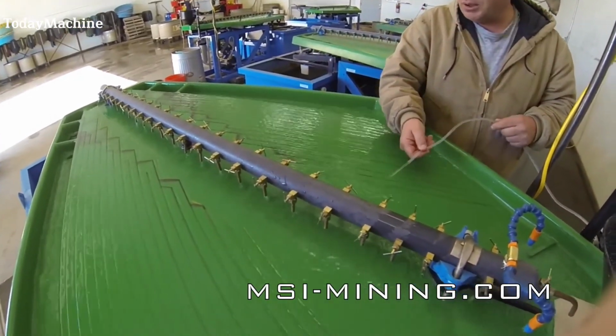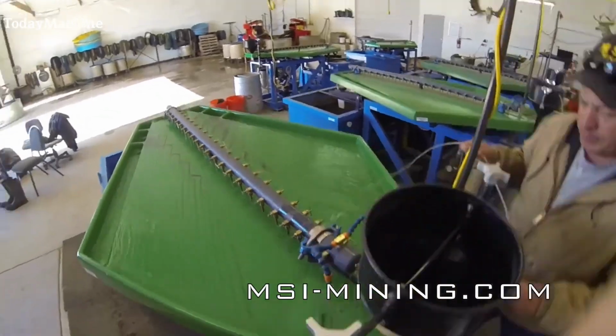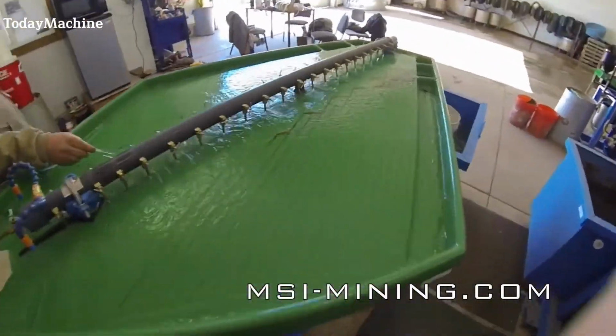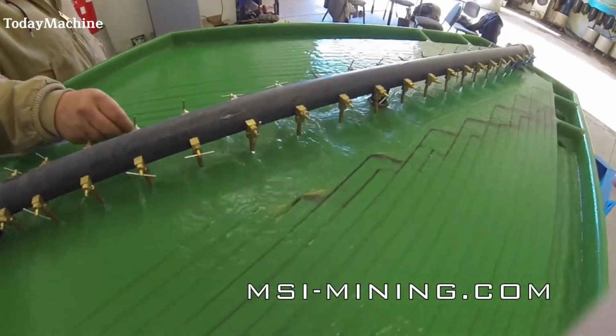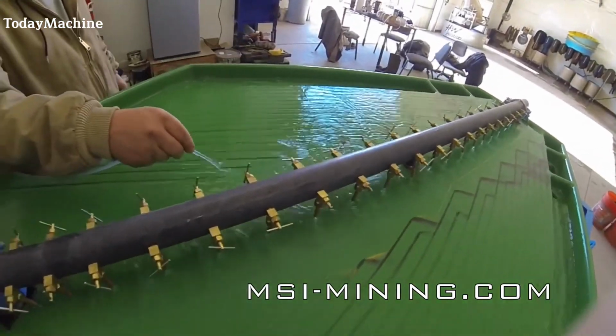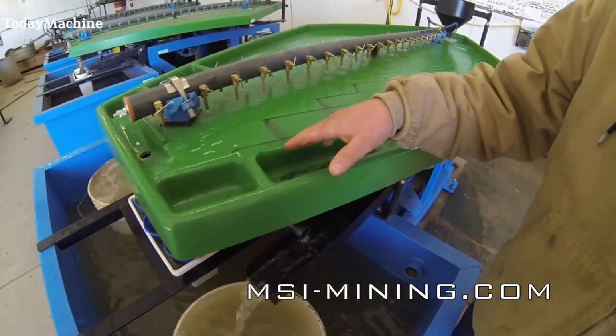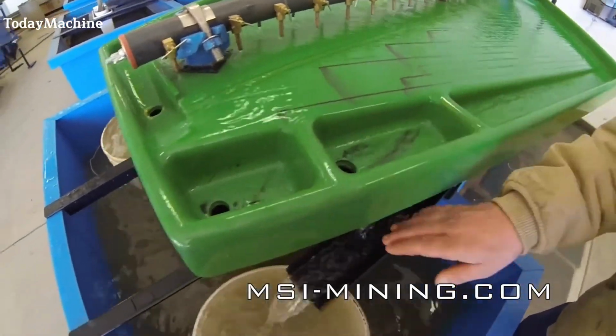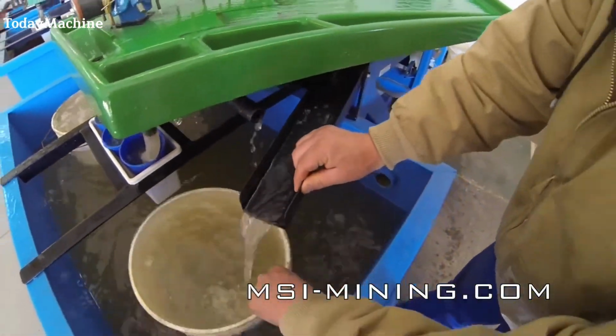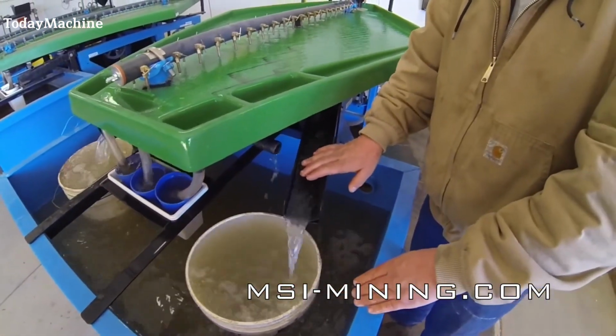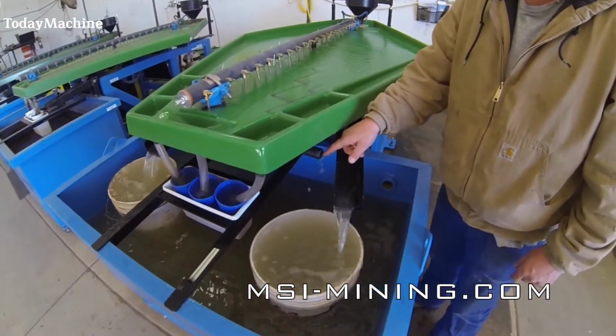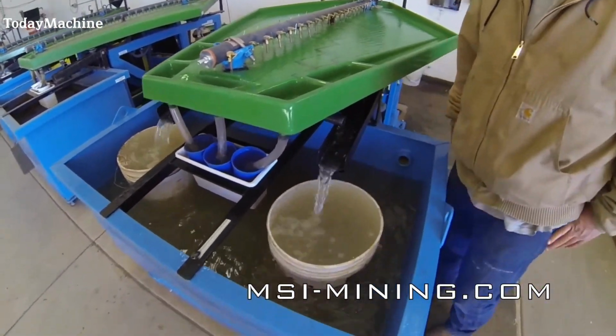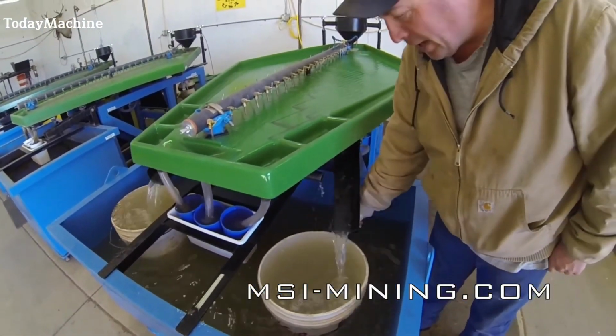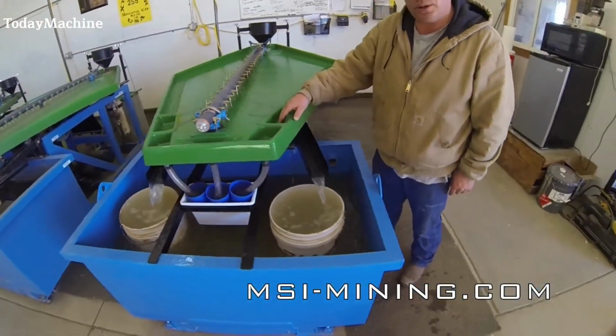Addressing gold losses. If gold losses are detected, screen materials into finer fractions and reduce feed rates. Test different mesh sizes and observe performance to identify optimal settings. Cleaning between runs. Remove leftover material and thoroughly clean the table and water systems to maintain performance. Use clean water to flush out grooves and collection ports to prevent clogging and contamination.